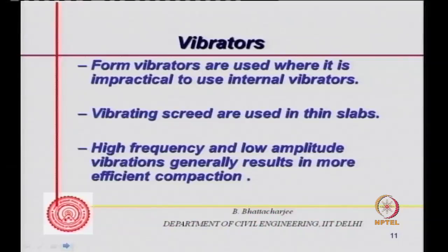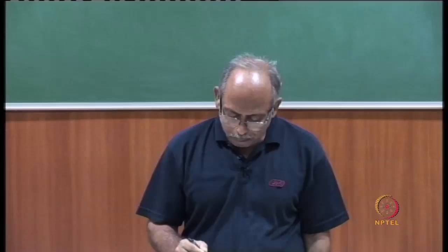High frequency and low amplitude vibration generally results in more efficient compaction. So that is the case with thin ones. The thinnest needle vibrator is actually most effective, but its radius of action is also low, so your effort in moving it has to be relatively high.